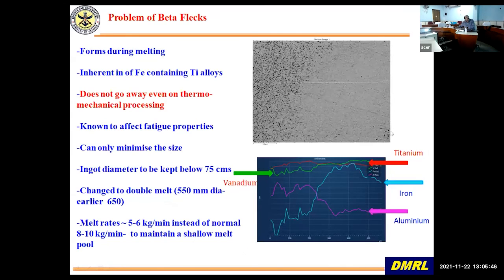So here I'm showing you what a beta flecks is. This is a heat treated material. Again, I will show you another microstructure, and this is a scan for composition. You can see in this region there is a jump in iron composition. So this region has higher iron composition as compared to this. So the beta transus of this region will be relatively lower as compared to this.